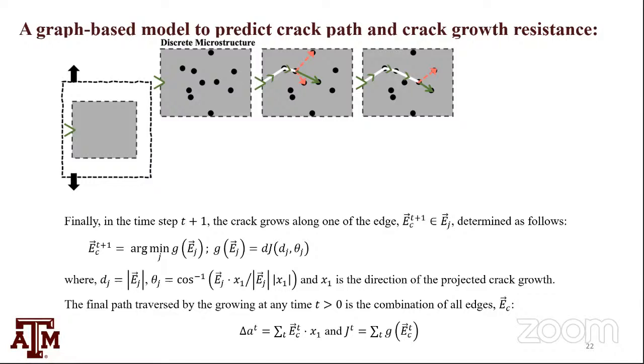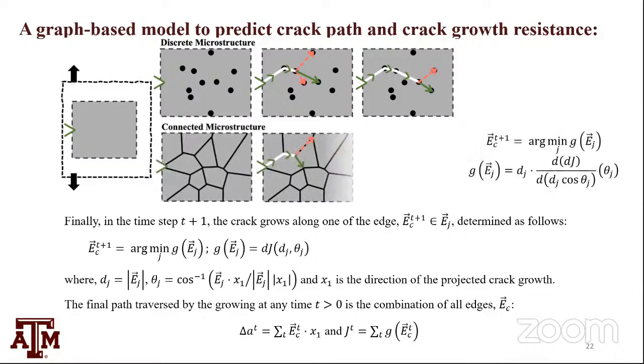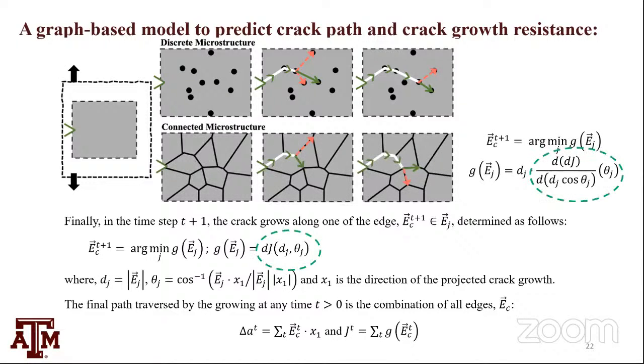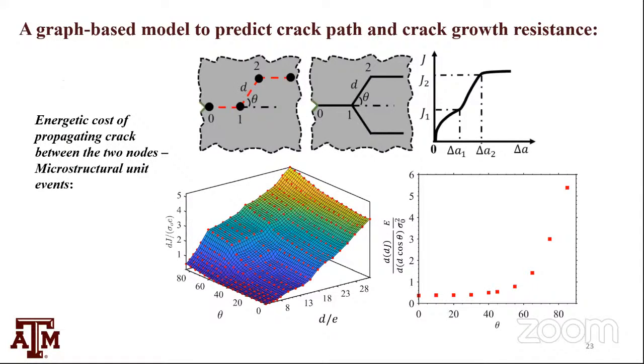Yeah, you're right in that. So what we found, this was the interesting part. The same thing came in our mind. This is ductile fracture, right? So the matrix follows Gurson. And we did this calculation, but this is small scale yielding. But you're still right that we still have a scaling of plastic dissipation. So we were shocked. Why did it work when we started to sum them together? Even in the grain boundary case, why did it work? The point here is that the summation kind of worked because the dissipation follows a power law. The plastic dissipation in some way will follow a power law as a crack keeps growing. But delta J stays the same way and it adds up.